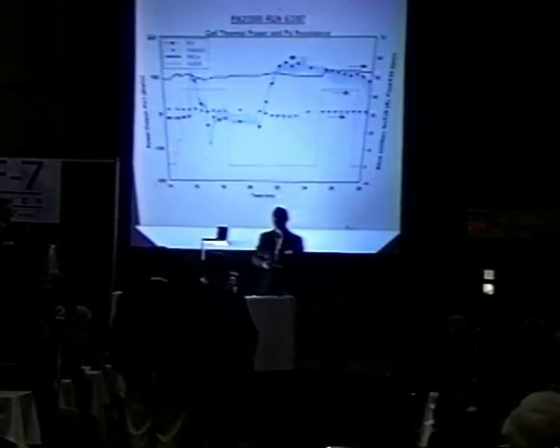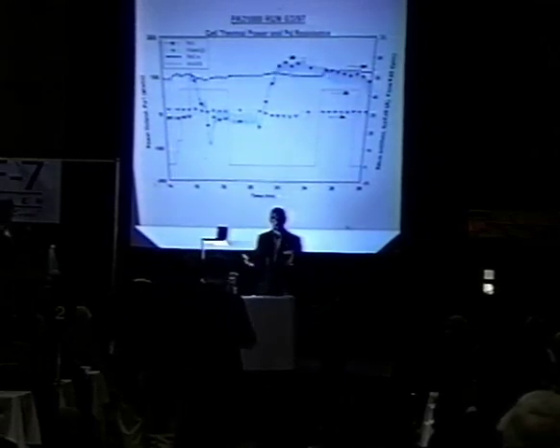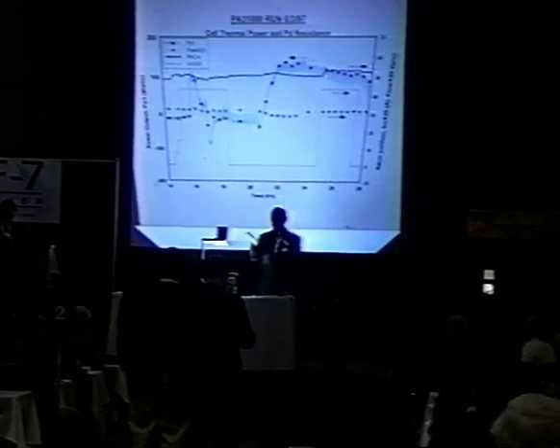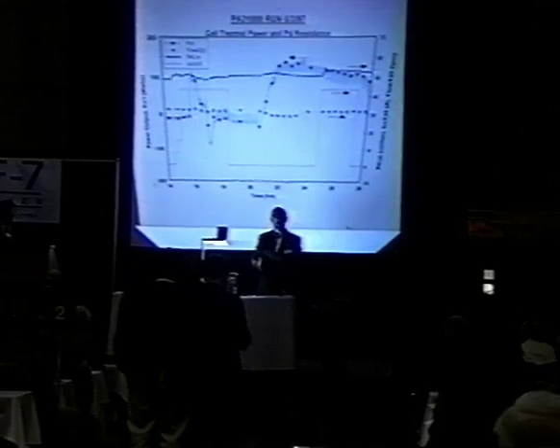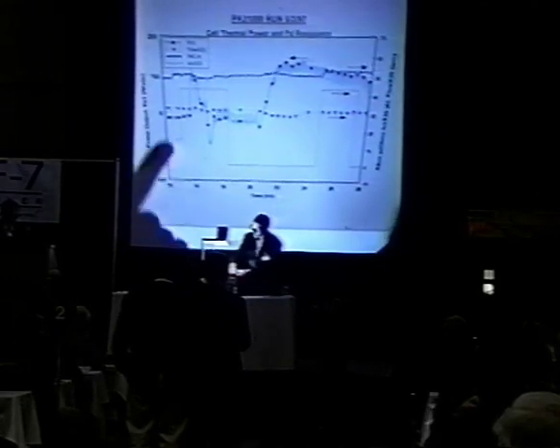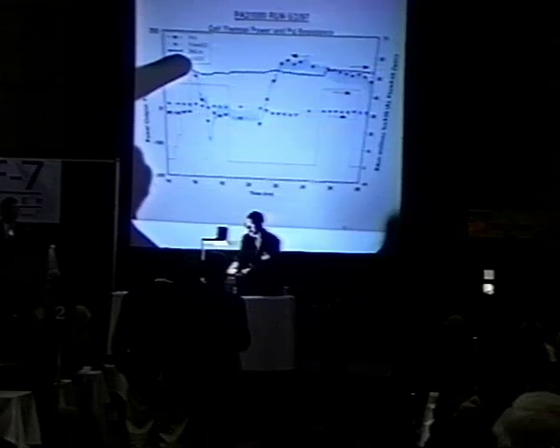Most of these cells that I've run typically require about 80 watts or so. Say if I want to keep this at 60 degrees centigrade, it takes typically 60 watts. And what you're going to see, obviously, when you start cooling the system real fast, then you're taking heat out of these cells. And that shows up as a positive power spike in these plots. In fact, right here is one. This was during the cooling, where you see that power going positive.